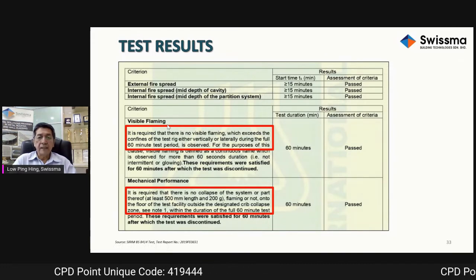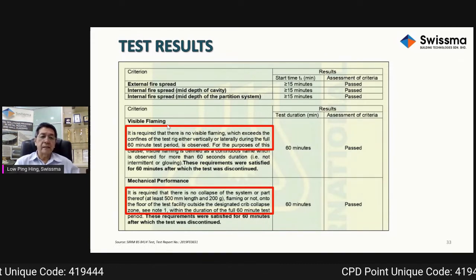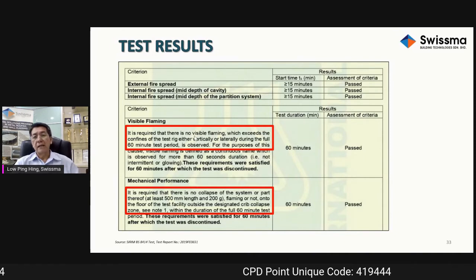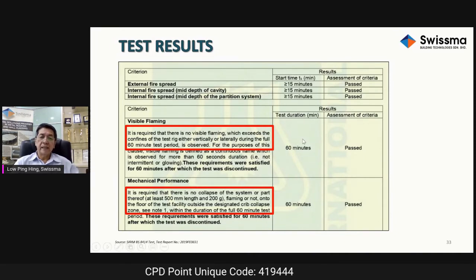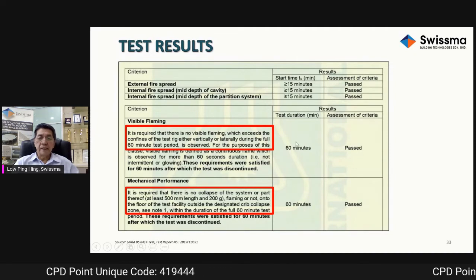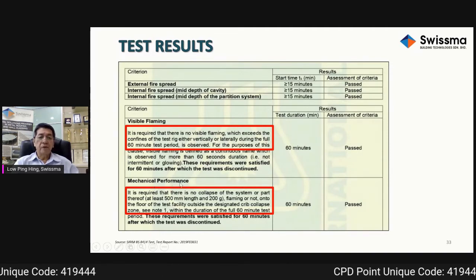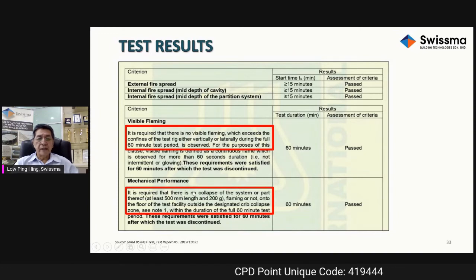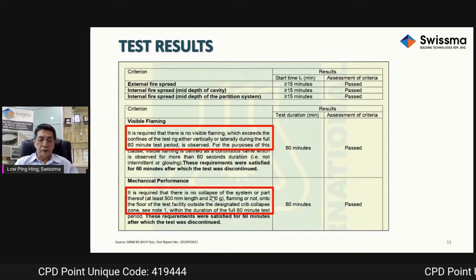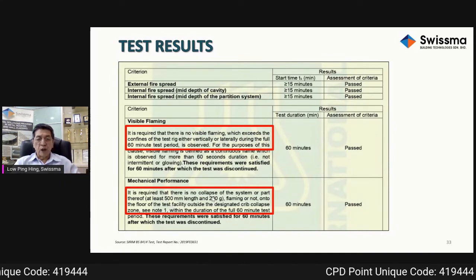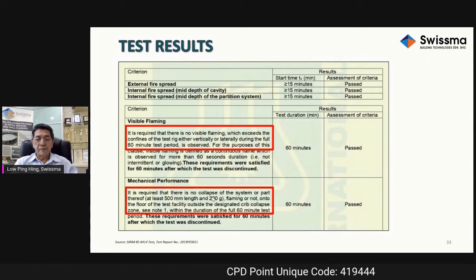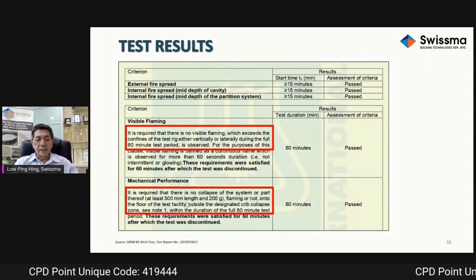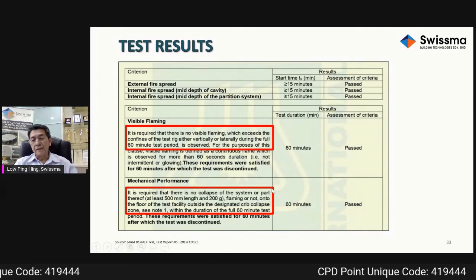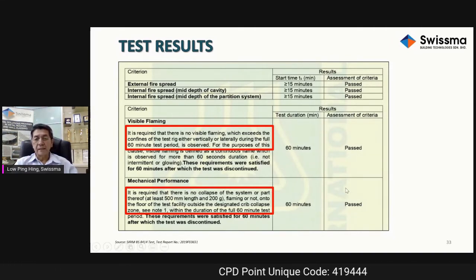Next criterion, the visible flaming. As explained by Rocky, the flame cannot exceed the confines of the test rig vertically or laterally. And in our test, it was well within the confines. Mechanical performance: again, they will measure whether any objects fall outside the crib collapse zone. So they are very specific. Any object that falls out of this collapse zone with a certain length and weight is deemed a fail. And in our test, we pass.